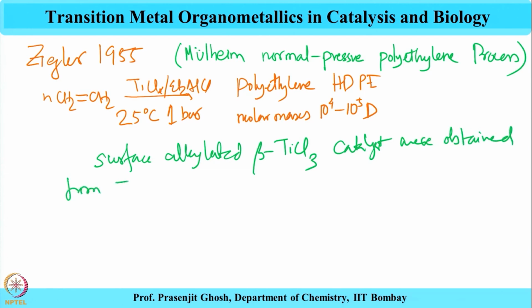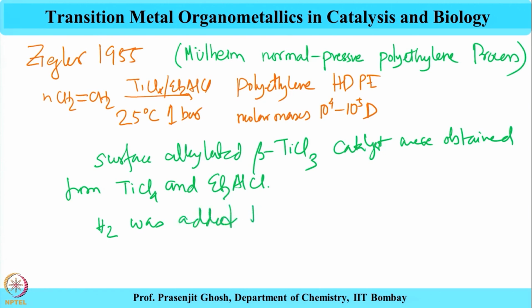from TiCl4 and diethyl aluminum chloride. And for obtaining lower molecular weight, hydrogen, H2, was added to control the polymer chain length.